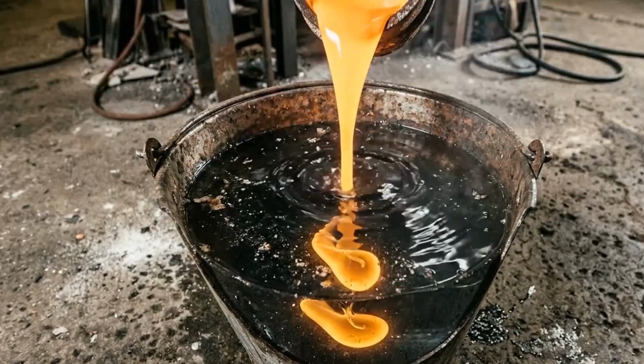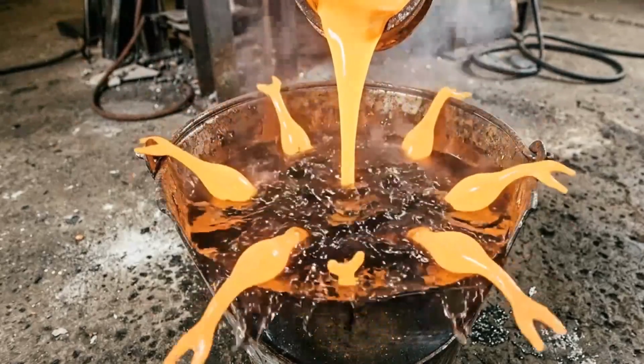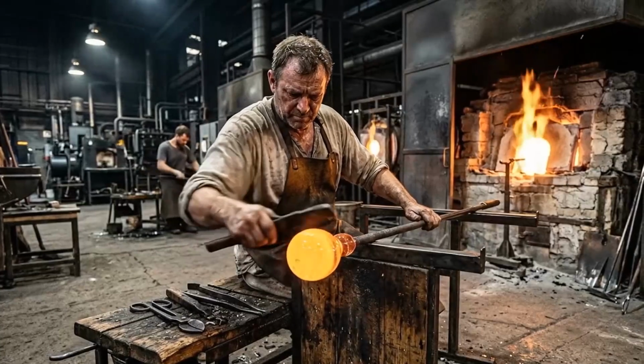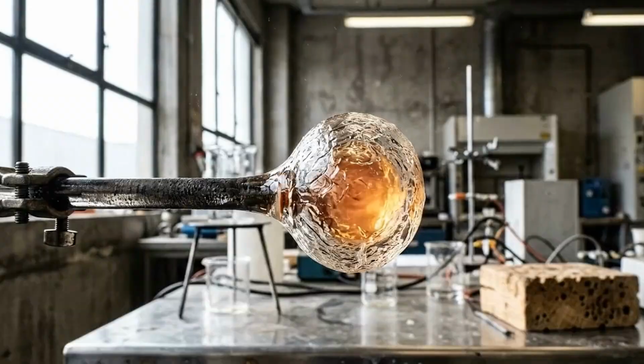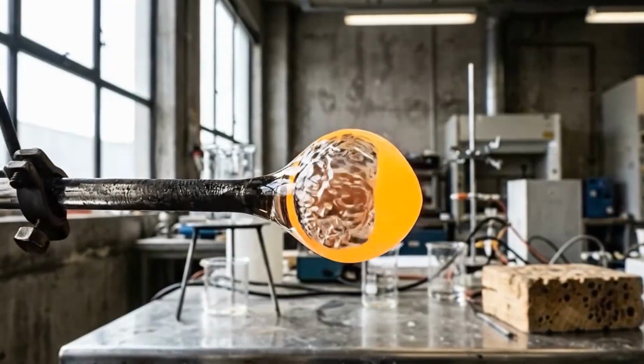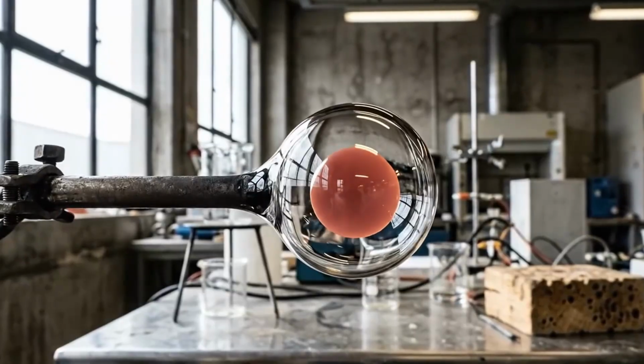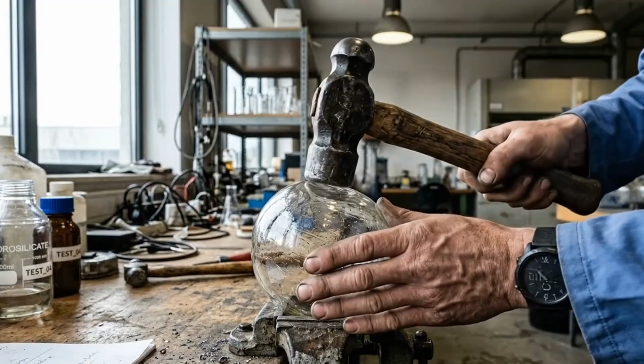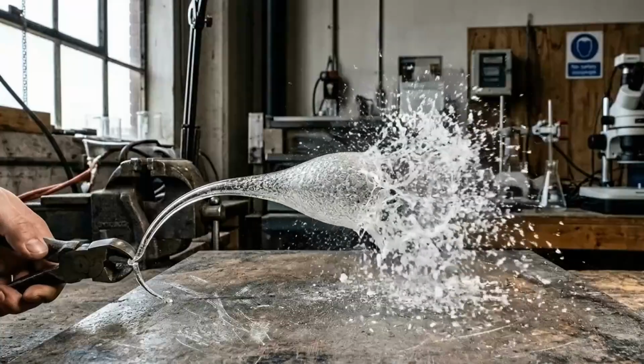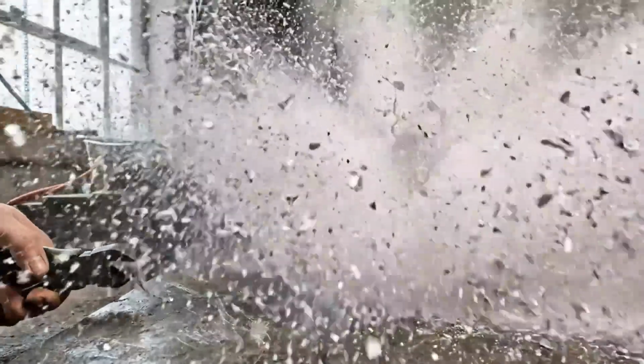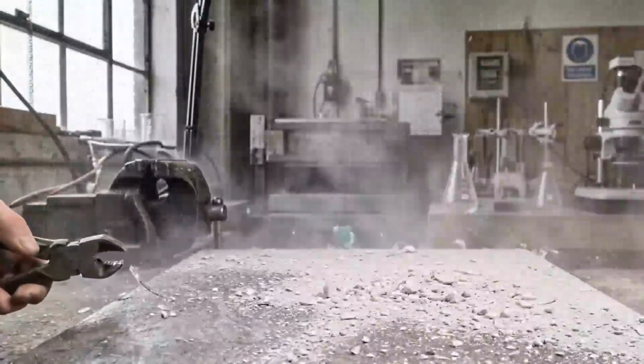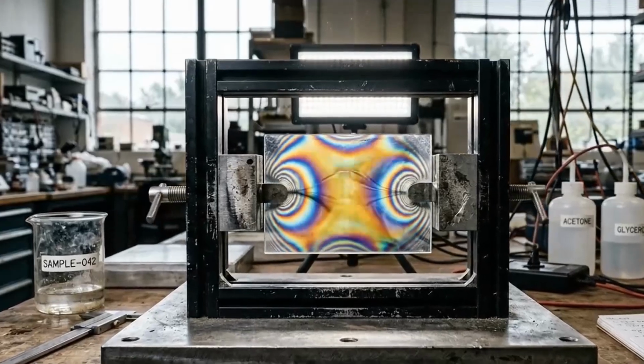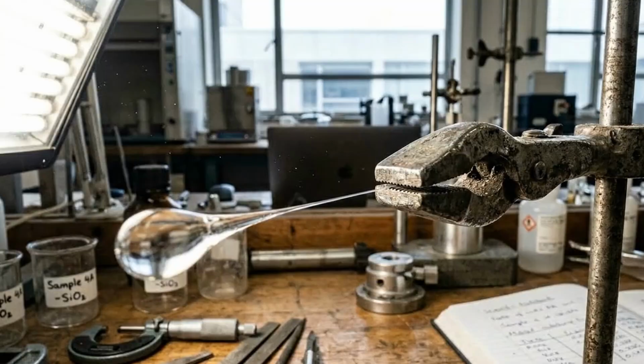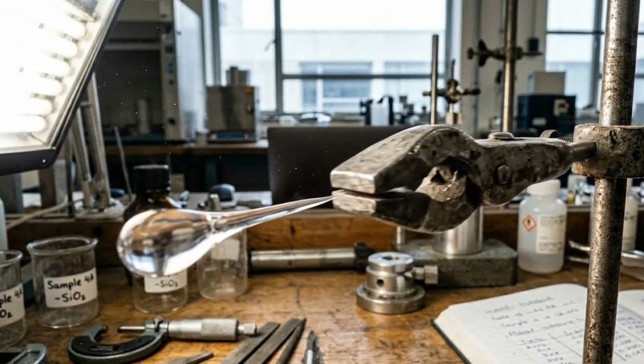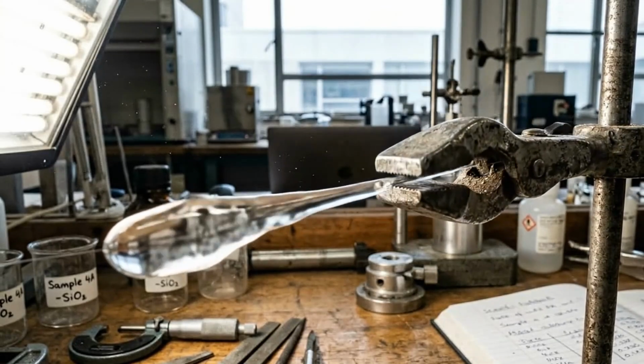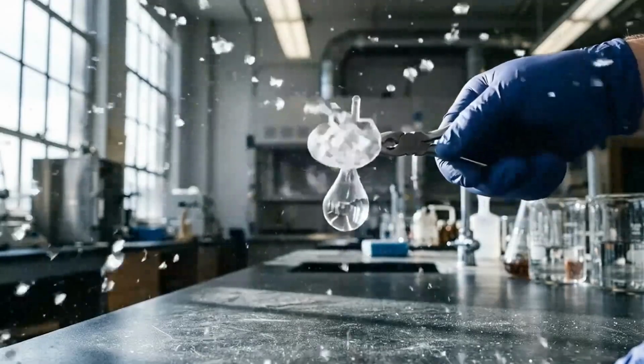In the 17th century, glassmakers would drop molten glass into cold water, creating a tadpole-shaped drop with a long, thin tail. The outside cools and solidifies first, compressing the inside. The result? The bulbous head can withstand hammer blows without breaking. But if you nick the tail, even slightly, the entire drop explodes into powder almost instantly. It's a perfect demonstration of extreme internal stresses. The head is under massive compression, stronger than some steels, while the tail is under extreme tension. One tiny trigger releases all that stored energy.